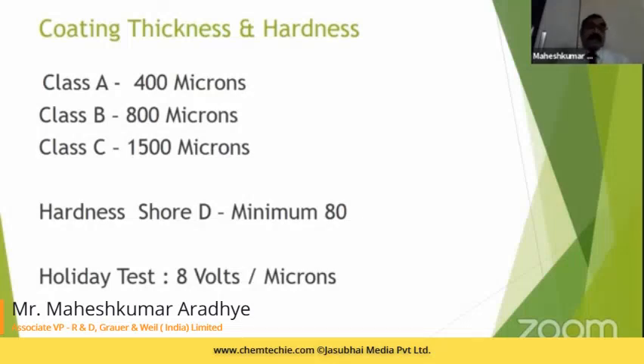Now, this is one of the very critical parameters. Another parameter is the holiday test. As a rule of thumb, in normal circumstances, whenever you go for holiday detection for any protective coating applied onto the surface, it is 4 volts per micron. But in EN 10289, the holiday detection test has to be carried out at 8 volts per micron, which is very high.